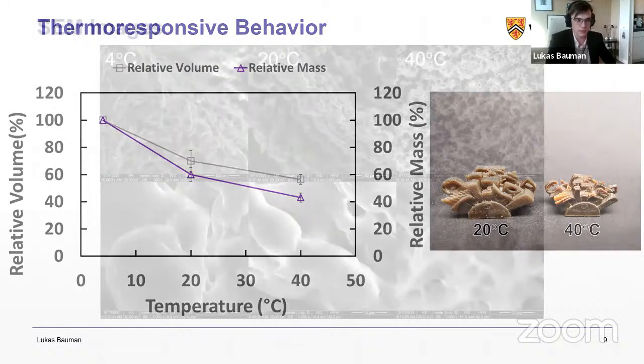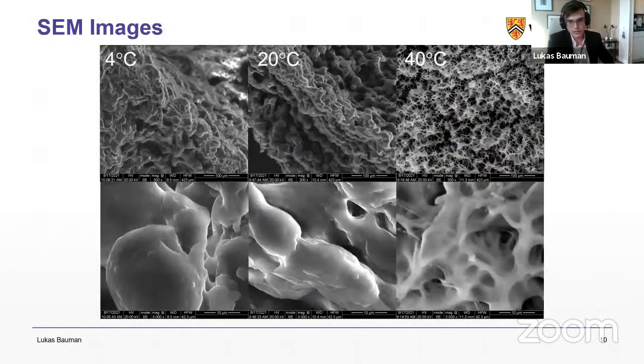Next, we have SEM images of these samples. So we can see at 4 degrees centigrade, it seems quite a bit more swollen. And then at 20 degrees, it's less swollen, more porous, and then extremely porous at 40 degrees, where it's fully deswollen and expelled as much water as it can.